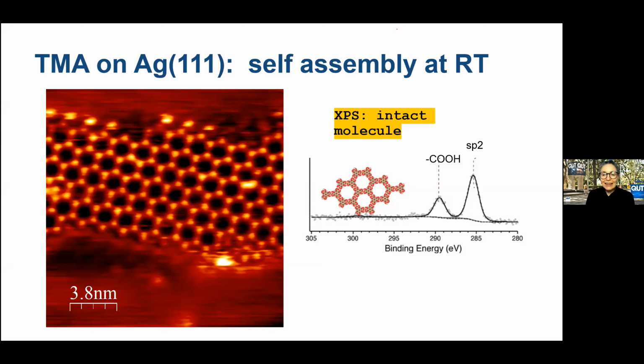What we did was to keep going with the annealing experiments, and we produced some rather beautiful phases doing this. After annealing to 200 degrees Celsius, we produced this non-periodic phase where we have central bright protrusions which are surrounded by 6 roughly triangular features. And what you'll notice is those are either isolated, where they appear a little bit like flowers, or they're knitted together so that they share triangular features with their neighbors.